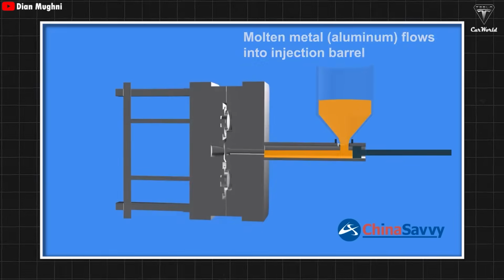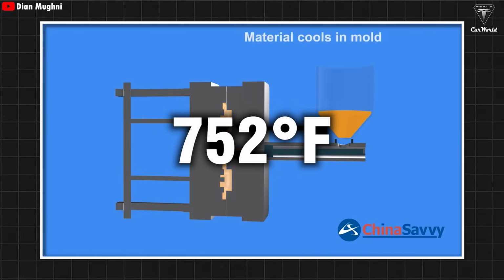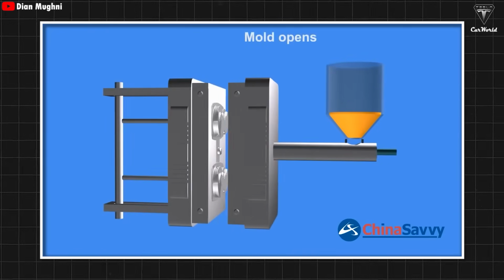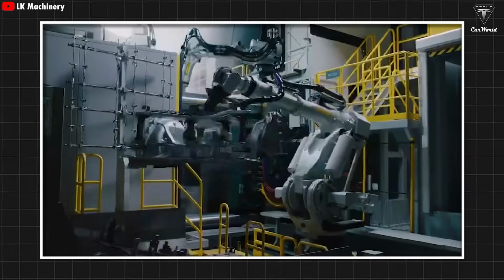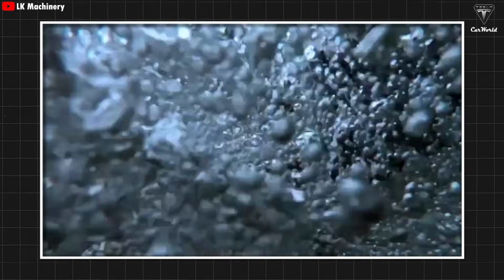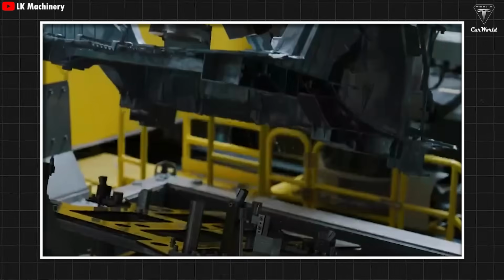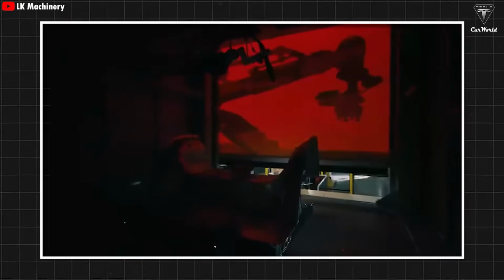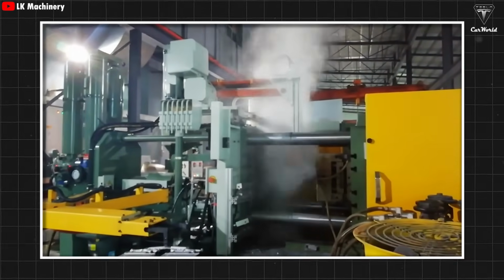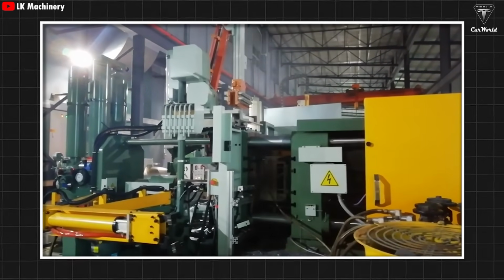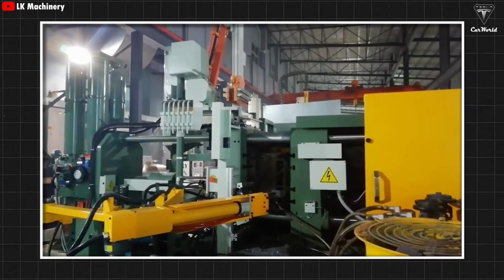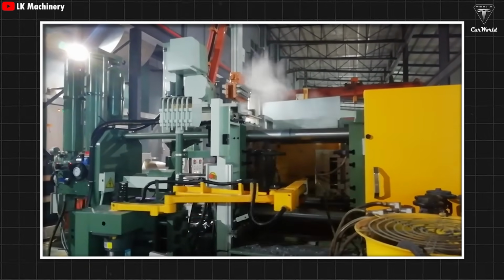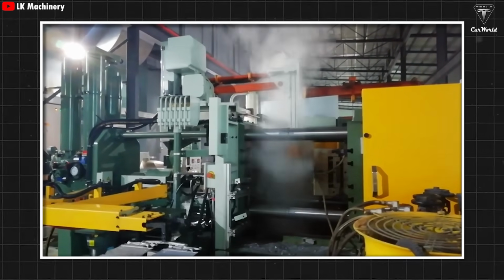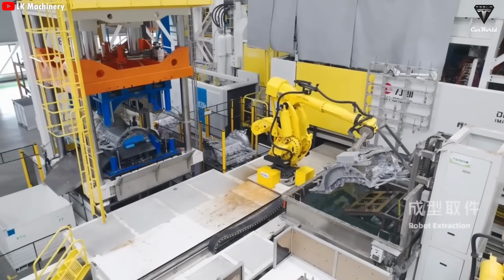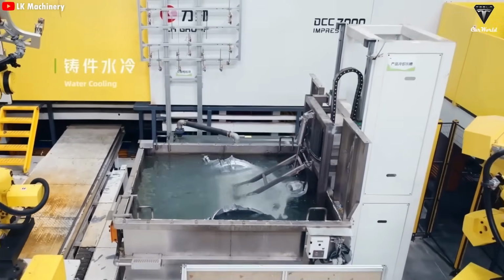The rough casting is ejected from the mold when it reaches about 752 degrees Fahrenheit and is immediately transferred to a cooling bath to rapidly reduce its temperature from 752 degrees Fahrenheit down to around 122 degrees Fahrenheit. This rapid cooling process not only effectively cools the material, but also helps eliminate certain defects that might form during solidification, while improving the aluminum's mechanical properties such as strength and hardness. Once the casting has finished cooling, the mold opens and is cooled down to around 365 degrees Fahrenheit. A robot then thoroughly cleans the mold, removing any impurities or leftover material, preparing it for the next casting cycle. This ensures that each subsequent cycle runs smoothly without any interference from leftover debris or contaminants from the previous cycle.